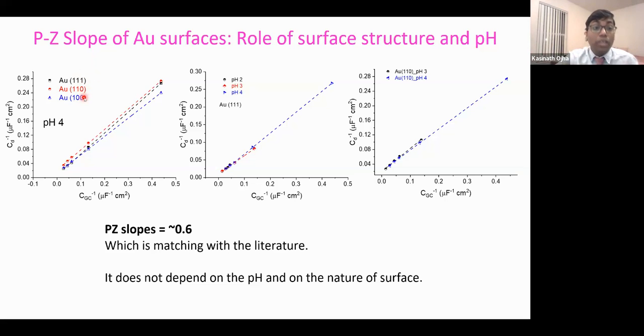And then for gold, it is a very ideal material to do the double layer measurements on different surfaces, because they have clear double layer regions. So I did 3 different gold surfaces and looked at their Parsons-Zobel slope, and they are exactly the same. They are not changing with the surface. I think this answers the question about the surface and structure of the material. And I also changed the pH, and pH also doesn't change the slope, even for other surfaces as well.